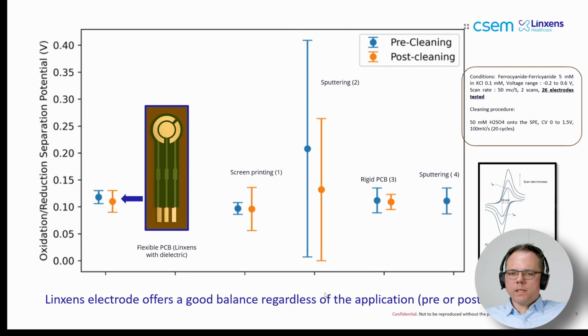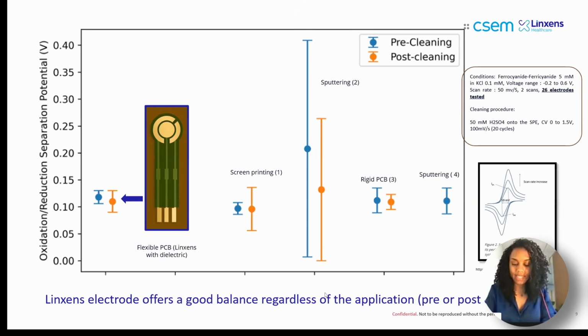And so when it's under stress, you don't have cracks or something in the gold layer that would expose the beneath lying metals. No. Because for the story, Linxens comes from the manufacturing of microconnectors for credit cards in the past. So we well know the constraint on the flexibility, and our technology is compatible for any mechanical constraint. And we are creative to create something where whatever the deformation that you will apply, the metal will stick, and the gold will keep the properties that it has.